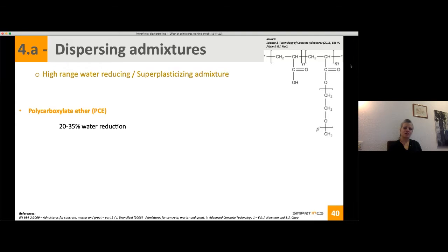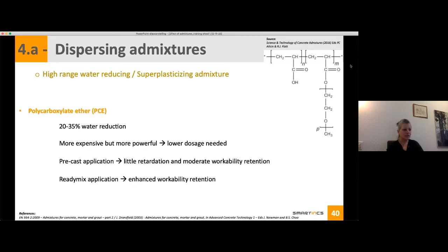Nowadays, I think that more than 85% of the superplasticizers are PCE based, and the expectation is that in the future it will be more and more PCE based. You can see PCE already brings higher water reduction compared to what you have with your melamine or your naphthalene, 20 to 35% water reduction. And if you just look at the raw material, they are more expensive, but you can see with performance, they're also more powerful. So it's more expensive, but you will use a lower dosage, with better properties. So in the end, it won't bring extra cost in using them. They are used in precast and ready mix applications.